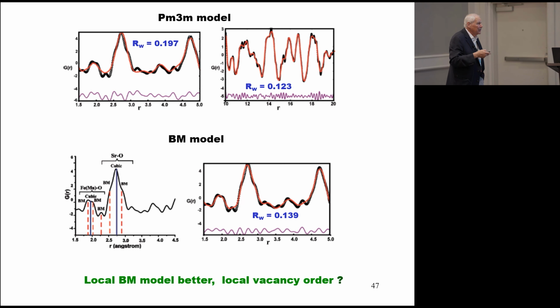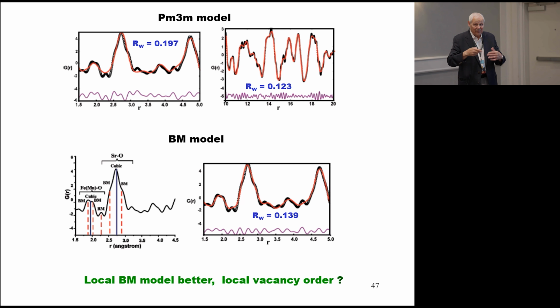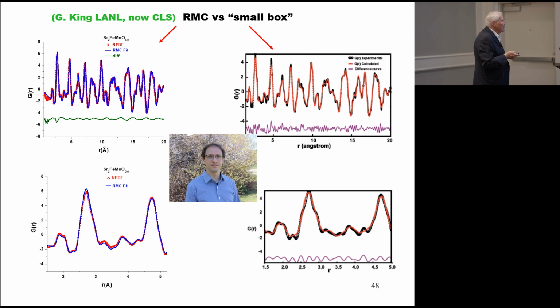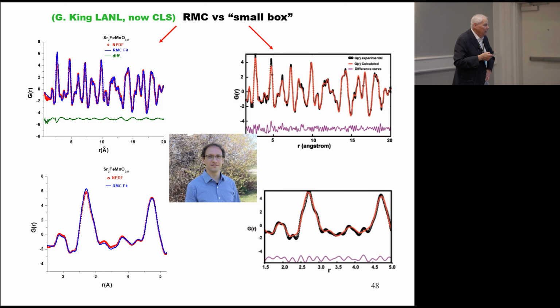However, again, within the spirit of the small box approach, if you now go to something like a Brownmillerite model, of course you get a better fit, and of course that's not a big surprise. You have many more adjustable parameters to play with. Now, when we were doing this work, the RMC techniques were just sort of emerging, and so we were working with Graham King, who, as far as I know, was the last instrument responsible at the Lujan Center for the PDF instrument. He now works, interestingly enough, at the Canadian Light Source.